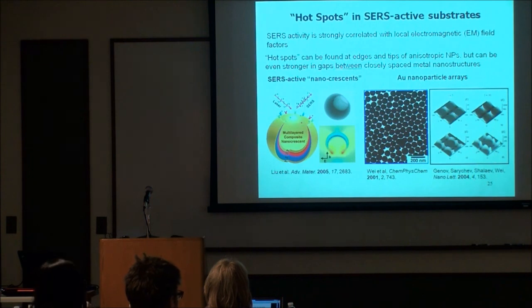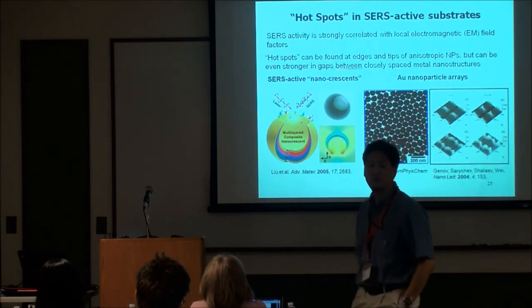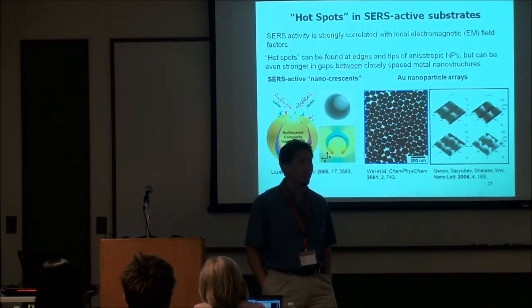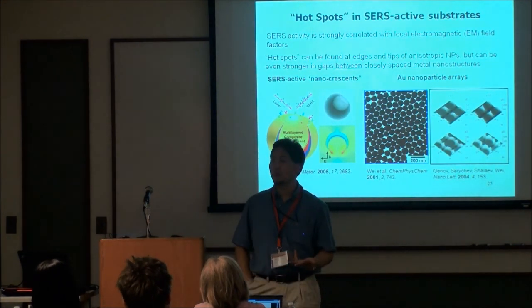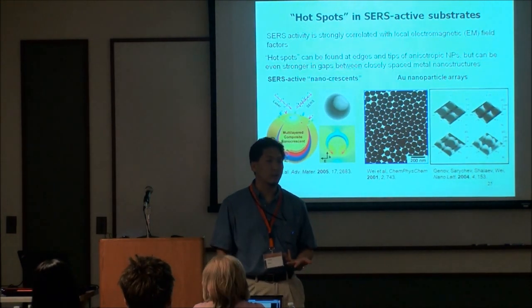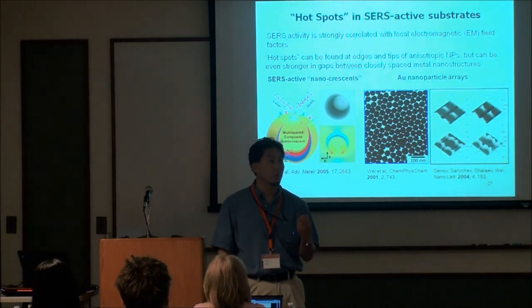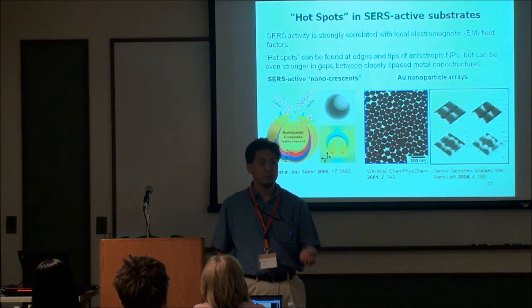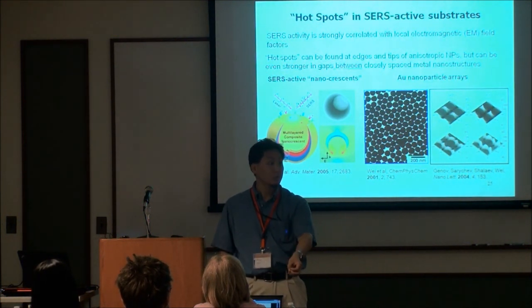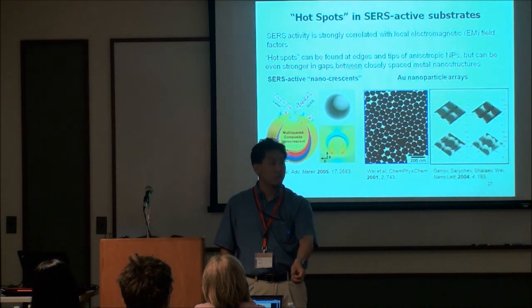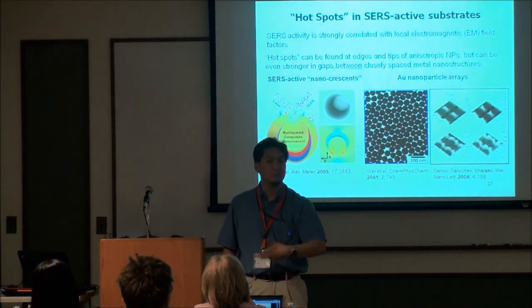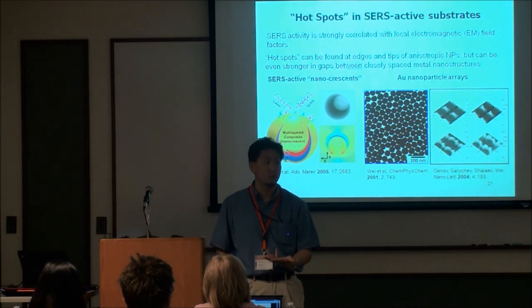The shell that protects, the organic shell or the gold shell? The organic shell. Okay. So the question was, for a practical consideration, if you functionalize a particle, how long lived can you expect it to be in a biological solution? The answer really lies in the details of the materials put on here. If you're thinking about the displacement of molecules that are attached, say, by sulfur ligands, then the displacement can be on the order of about a week before you get extensive degradation. So most of the time, you generate something within the first couple of days, and then you use it.